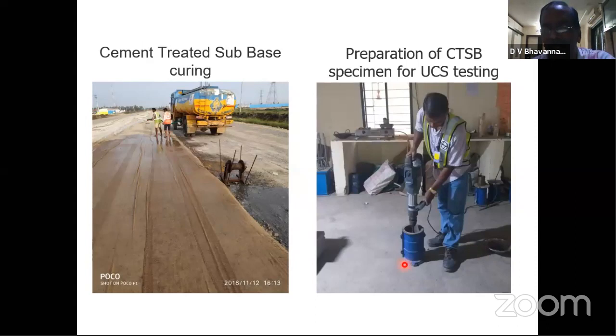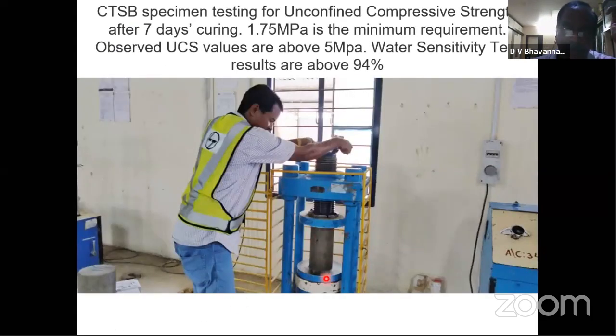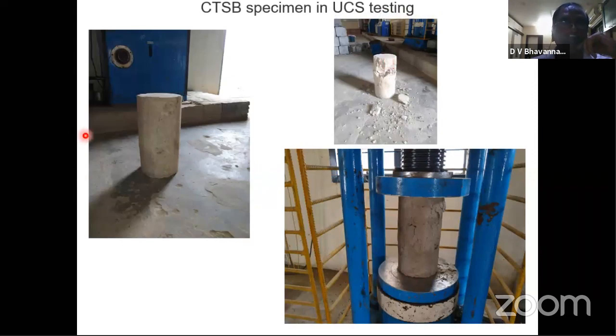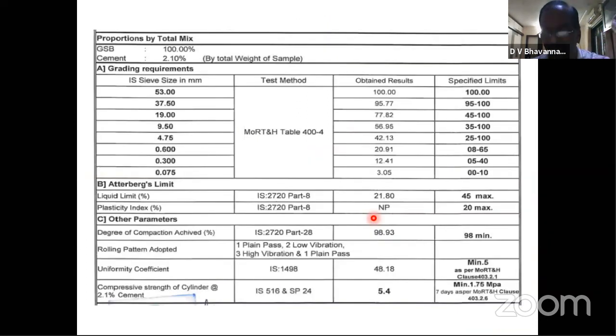And some specimens are cast for testing the unconfined compressive strength test. Here the specimen is like this. Here the required UCS is 1.75 MPa, and here we are getting more than 5 MPa. Also, the water sensitivity test is done after immersing the specimens for 24 hours and testing again. The strength retained is about 95%, 94%. The specimens you observe. The summary of the test results.